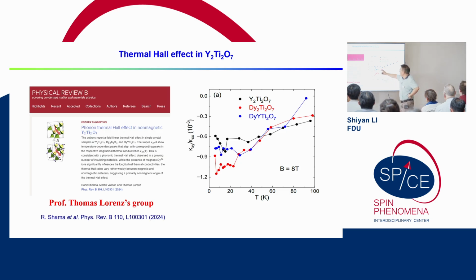But anyway, last year they rechecked the thermal Hall of these three compounds, this Y2 and 2 oxide. They measured that these signals are indeed real. These non-magnetic and magnetic compounds have similar thermal Hall. So that means this indeed supports our claim of a universal thermal Hall effect in all single crystals.